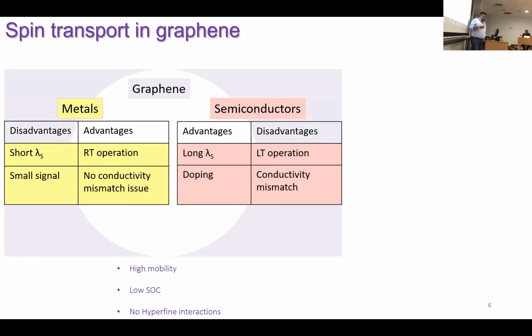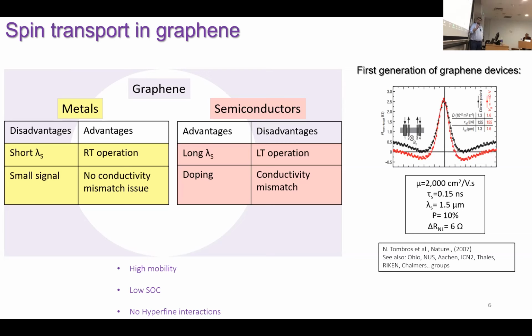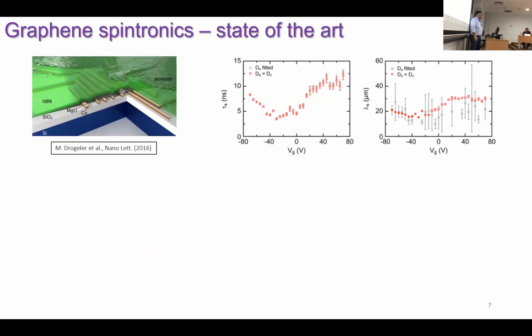And so the hype with graphene was that it was believed it would inherit the advantages of both metals and semiconductors, meaning that since this material has extremely high mobilities, and since it's just carbon 12, the spin orbit coupling strength is extremely small, and there is no hyperfine interaction. So the expectation was that this should translate into very long spin relaxation lengths at room temperature. This was the first experimental result, and the results were both quite positive and a bit negative, because the good thing was it was working at room temperature, but the bad news was the spin relaxation lengths were also not that long.